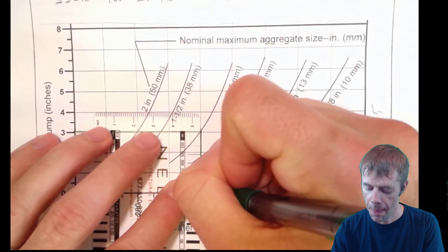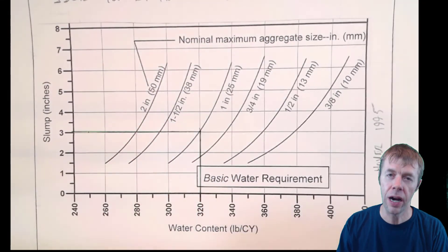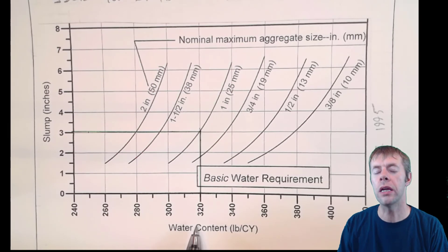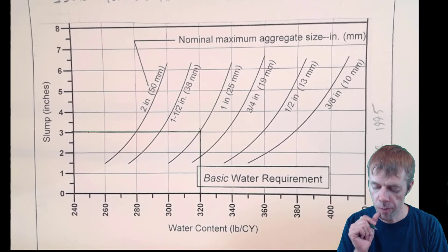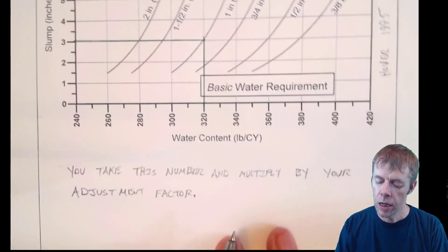And then go down here. It says that I need 320 pounds per one cubic yard. 320 pounds per one cubic yard. That's cool. But remember,